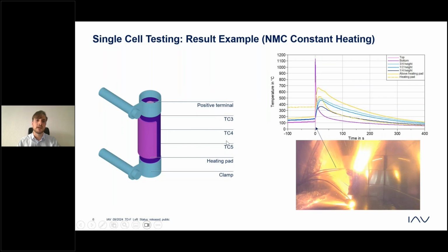And we placed different kinds of thermocouples, as you could see earlier, which are measuring the temperatures on the cell. And as you can see here, we can directly see how the cell goes into this thermal runaway, and the temperatures are getting higher, especially the gas temperatures we measured, where you can see that the temperature peak is really, really high. And then we have later on a cool down phase after the runaway.